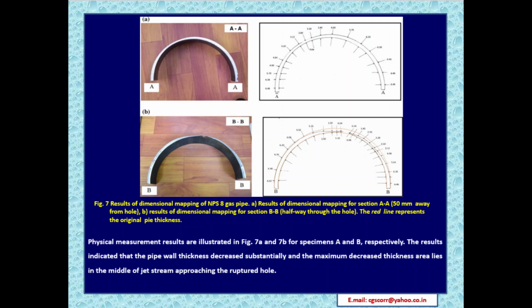Figure 7 portrays the results of dimensional mapping of NPS 8 gas pipe. Figure 7A shows the results of dimensional mapping for section AA, 50 mm away from the hole. Whereas B represents the results of dimensional mapping of the section BB, halfway through the hole. The red line represents the original pipe thickness. Physical measurement results are illustrated in the figure 7A and 7B for specimens A and B respectively. The results indicated that the pipe wall thickness decreased substantially and the maximum decrease in thickness lies in the middle of the jet stream approaching the ruptured hole.